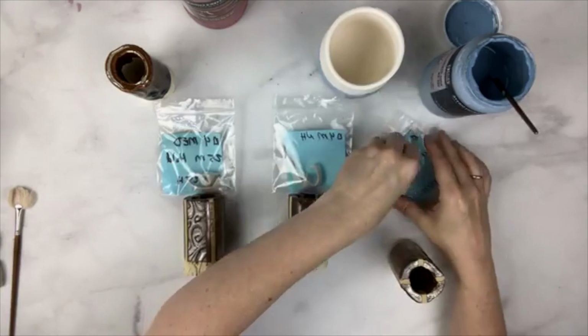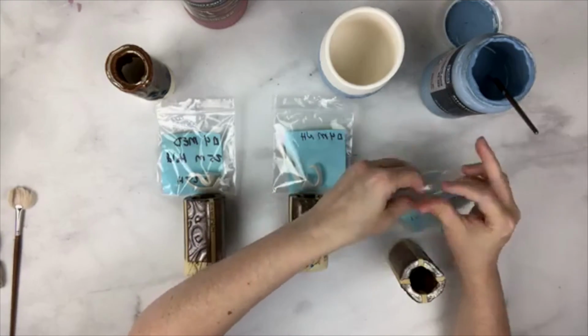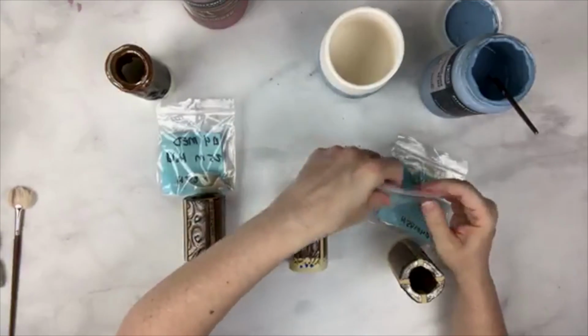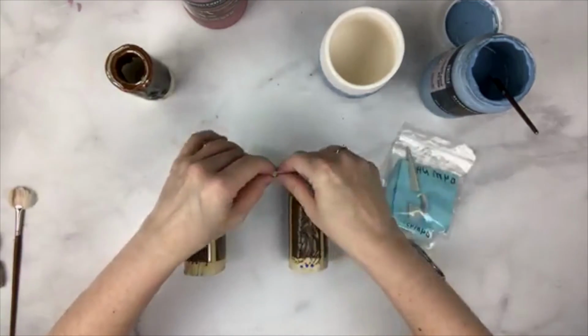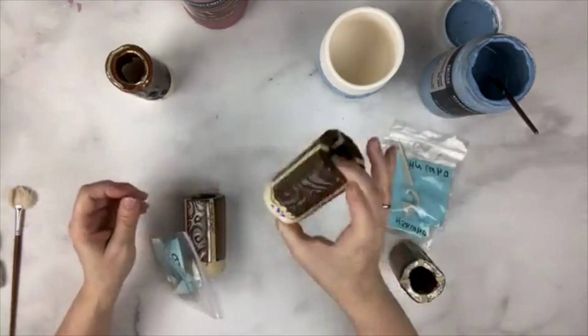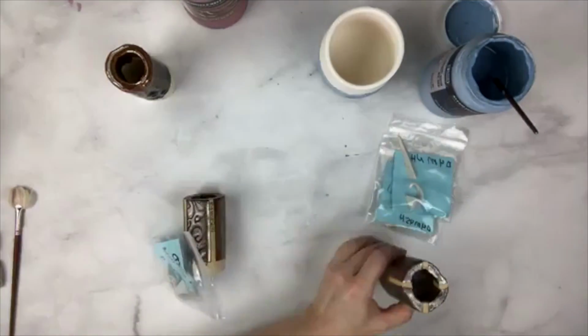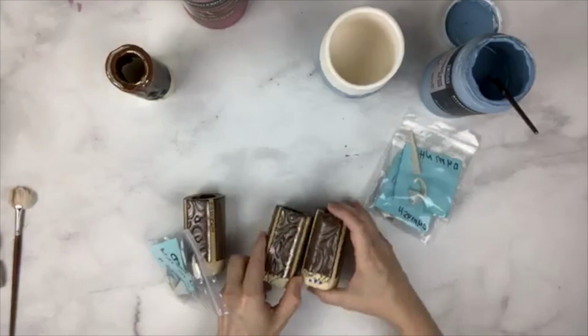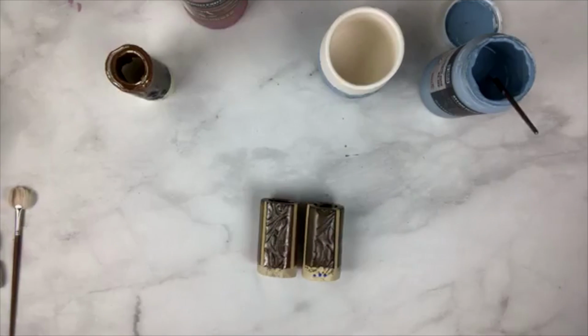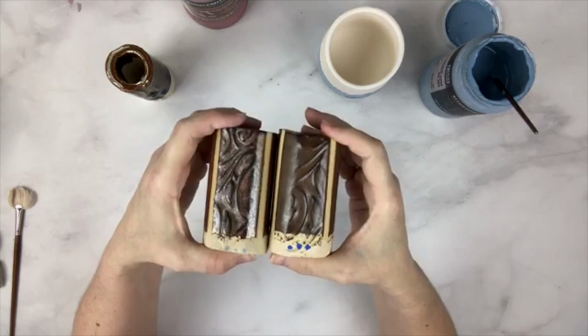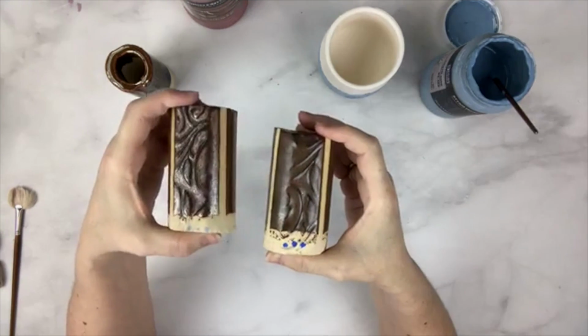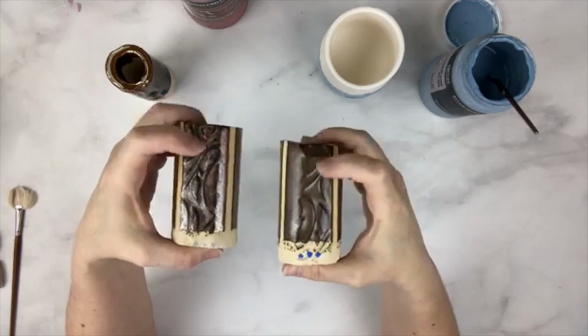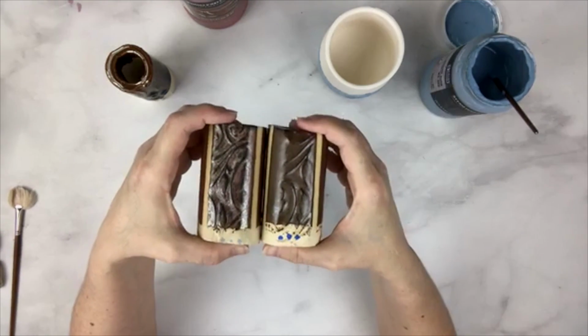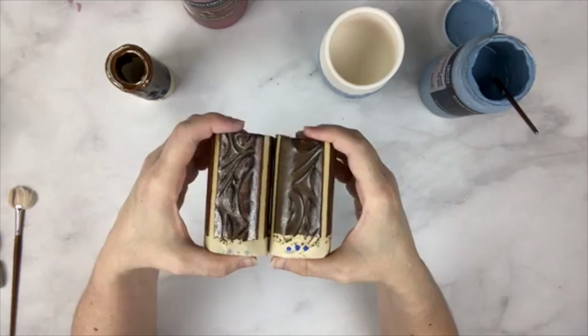5 firing. So if your kiln is not quite firing to cone 5, you may get results that could be anywhere from kind of dull to expected, depending on the amount of heat work. This shows you the importance of cones in your firing, because both of these were fired to a scheduled cone 4. This one had a long hold, so it actually went to cone 5. This one did not. So just because you schedule it for a particular cone, it's not necessarily at that cone. You really need to use witness cones in your firing.